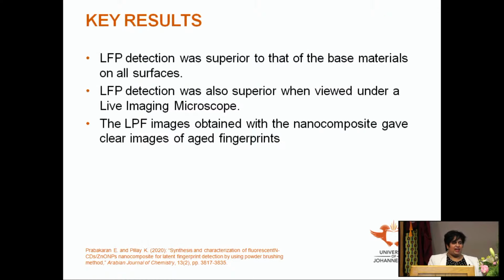So some of the highlights of this study was that the composite material showed superior latent fingerprint detecting abilities as opposed to the base materials. Now what I mean by that is that the zinc oxide nanoparticles on their own and the nitrogen-doped carbon dots on their own were not as effective as the composite material. The fingerprint images could be clearly viewed under a live imaging microscope.